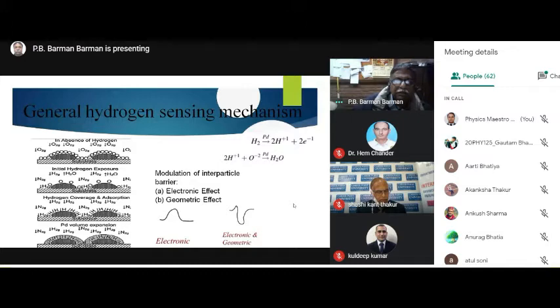So this is the general mechanism, and we went further to find what exactly is happening. When we talk of the general hydrogen sensing mechanism, in presence of hydrogen it forms the hydride, and ultimately there is a swelling in the palladium nanoparticles, resulting in volume expansion. The surface to volume ratio gets increased, resulting in a better sensing mechanism. Initially it was the electronic effect, followed by the geometric effect.